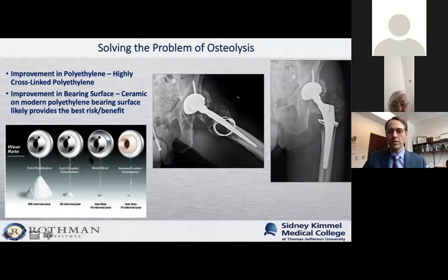The picture here helps to put things in perspective with just how much lower the wear rates have gotten compared to older versions of polyethylene. So when we look here, this is a picture of an older version of plastic with a metal head, showing that it wore at close to 200 microns per year. And then once we brought about the new polyethylene with that same metal ball, it brought our wear rates down to about 20 microns per year. And then if we take that same polyethylene in this scenario and go down here to this one where we put a ceramic ball in there, it shows that we wear down to less than 10 microns per year. And to put that in perspective, 10 microns is really 0.1 millimeters per year.